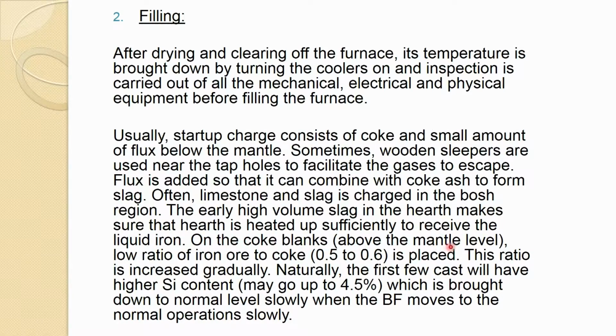So, on the coke blank above the mantle level, a low ratio of iron ore to coke, generally 0.5 to 0.6, is placed, and this ratio is increased gradually. Naturally, the first few casts will have a higher silicon content, which may go up to 4.5%, which is brought down to normal levels slowly when the blast furnace moves toward normal operation. When we say towards the normal operation, slowly as you bring this iron ore to coke ratio to the normal one, and then the normal operation is established, your silicon content is also reduced during that time. So, this is the filling process after drying